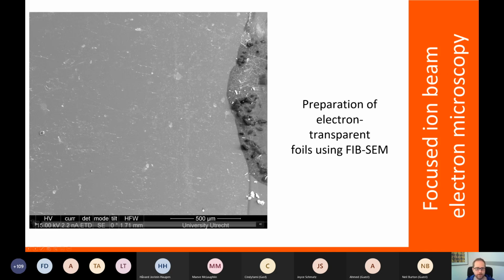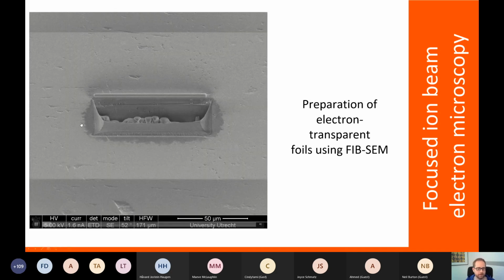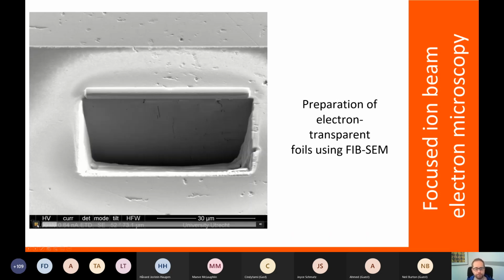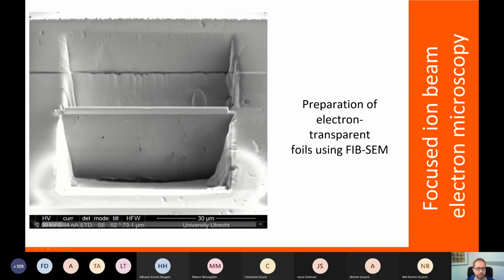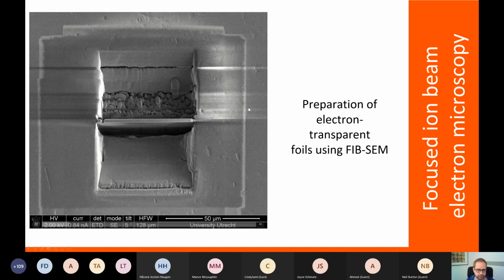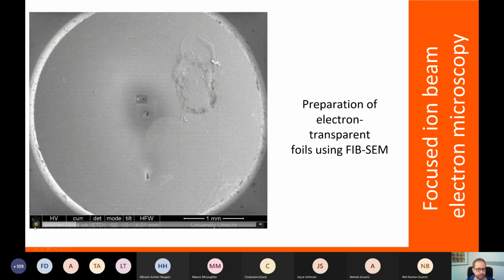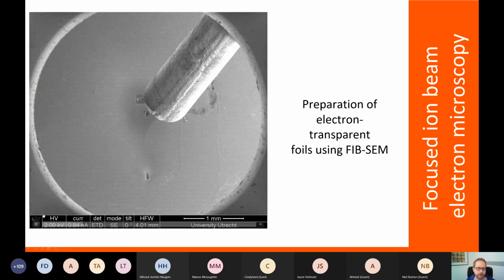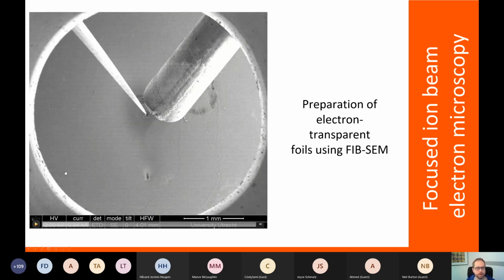So what you will see here is a little video again of how such a preparation works. We have a sample. We will cut a trench using the focused ion beam in front, but after we deposited a platinum layer or a tungsten layer on top of the sample to protect the area of interest, now we're building a trench in the front. You already see here some porosity, for example. Now we cut a trench in the back. We bring in the gas injection system again, and we bring in a needle, a nano manipulator that we can control with our mouse and keyboard. And you will see what we do with this in a second.